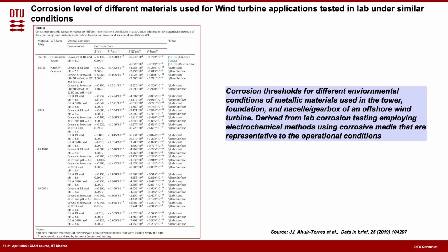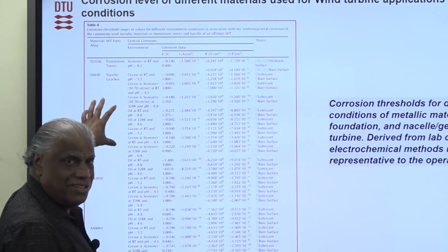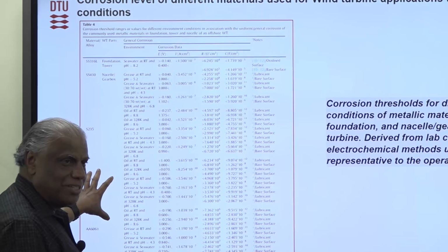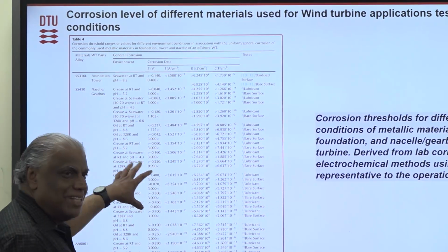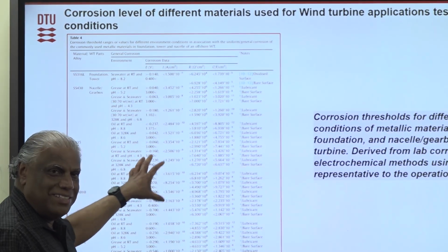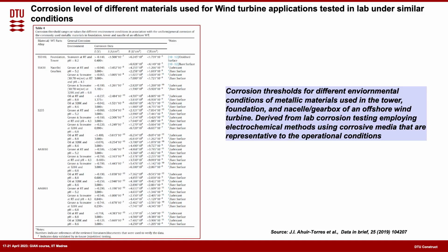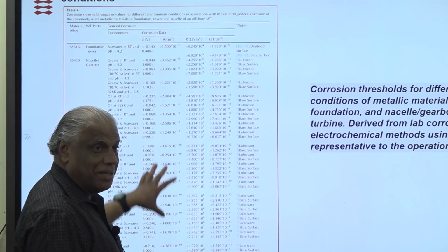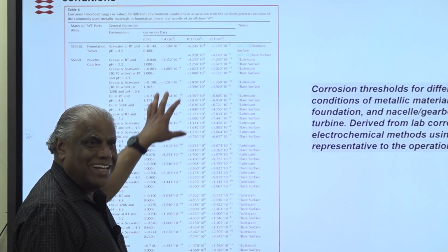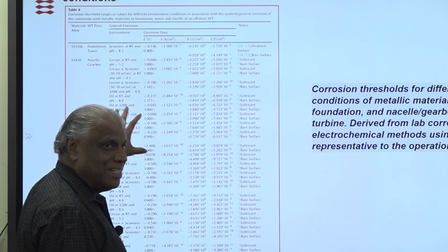So this is not coming from our study, but this is coming from another study, and that's the reason that I put that table, although it's probably difficult for you to read. What they did is they took these materials like the steel materials and aluminum material, which is used in the wind turbine, and they simulated the conditions which they see in the nacelle and other places. That condition they simulated in the lab, and then made the corrosion rate measurement from that.